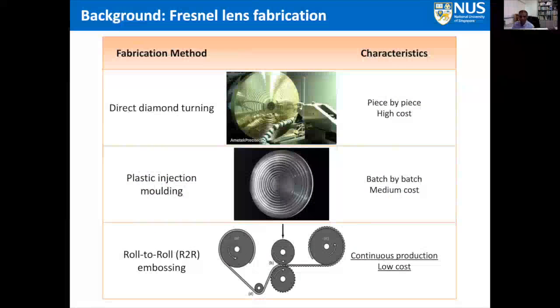So how do we fabricate them? The fabrication is done by direct diamond turning. In some instances, people use plastic injection molding. Of course, the best way would be by using roll-to-roll printing, or in this case, roll-to-roll embossing. Okay? And the biggest advantage is that it will become low cost if we use this technique. However, the cost of making the mold is high, and that has to be compensated by increasing the production so that we can have a large throughput and the cost can be significantly reduced.